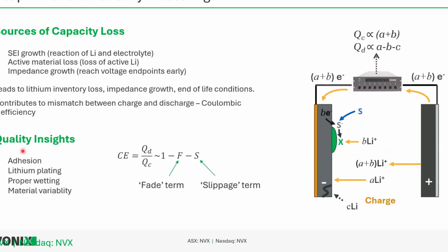And that's fairly straightforward. For quality insights, this can let us learn things about the proper wetting of a cell or lithium plating that's happening, material variabilities, some pretty basic things. And when we think about coulombic efficiency, which I think everybody uses in their work, but maybe is not appreciated as much as it could be or broken down into its constituents, this loss of capacity means that we're counting fewer and fewer electrons through our circuits on every subsequent charge discharge. And so our coulombic efficiency is going to be 1, a perfect cell, minus some kind of fade term.